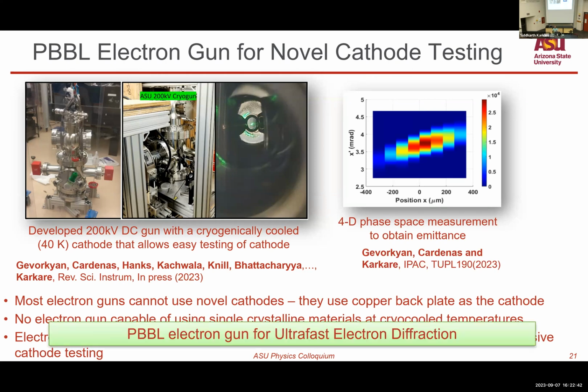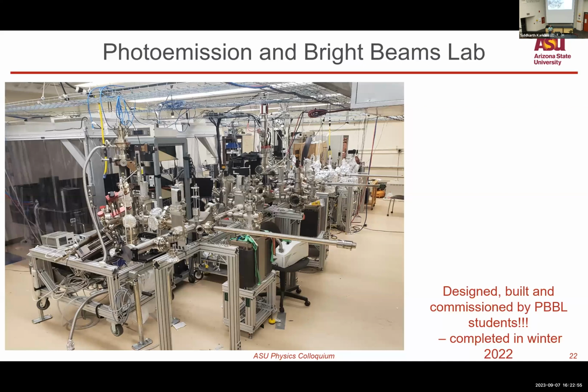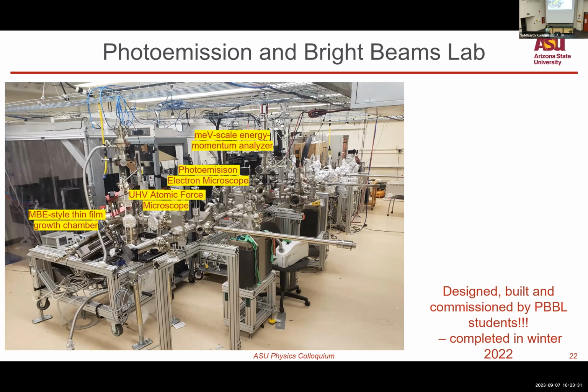This gun can also be converted into an ultra-fast electron diffraction instrument, which we plan to do in the next few years. So this is a picture of the photoemission and bright beams lab down in the Wexler Hall basement. This lab has been designed, built, and commissioned by my students in the photoemission and bright beams lab over the last few years. We've very recently completed all of it in 2022. We have an MBE-style thin film deposition chamber where we typically grow alkali antimonide materials. We have a UHV atomic force microscope where we can study the surfaces of these materials. We have a photoemission electron microscope. We have this millielectron volt energy scale electron analyzer that I told you about. And we have this electron gun. And all of these are connected in ultra high vacuum through this vacuum transfer line. It's a 30-foot long transfer line connecting all of these instruments.